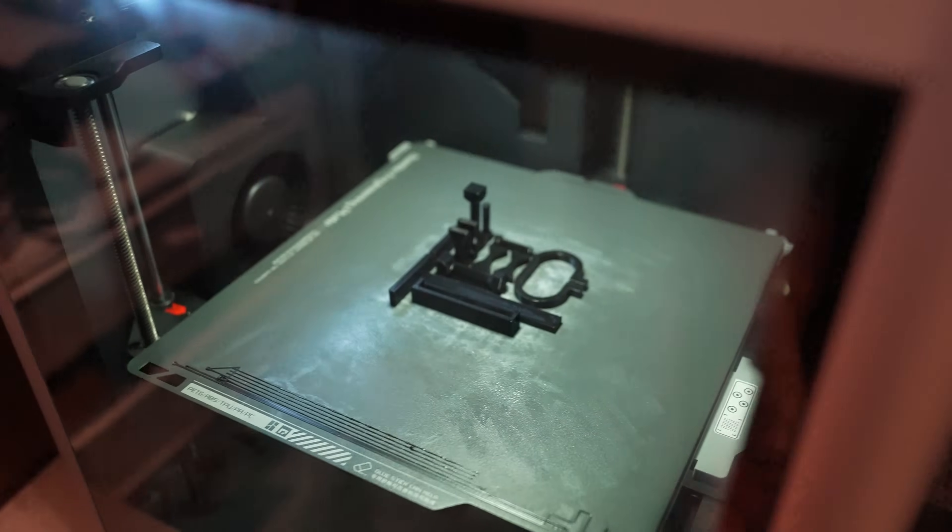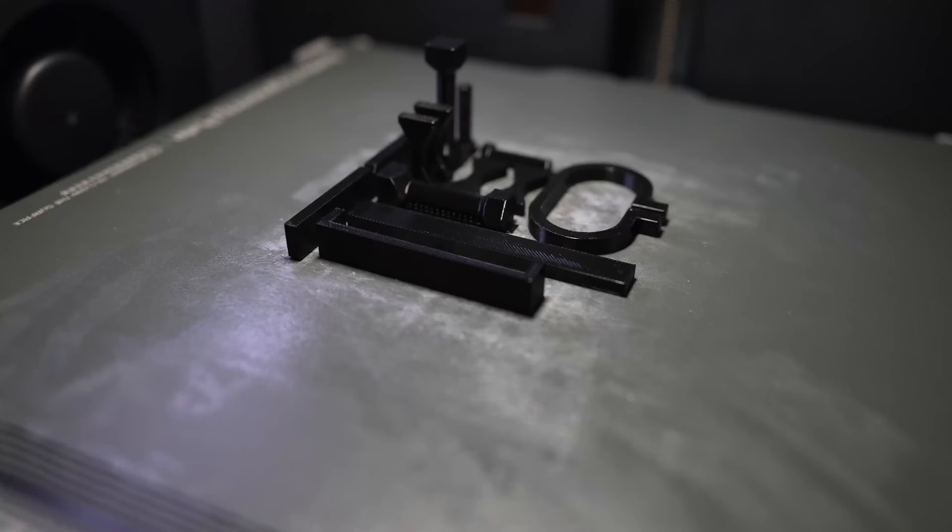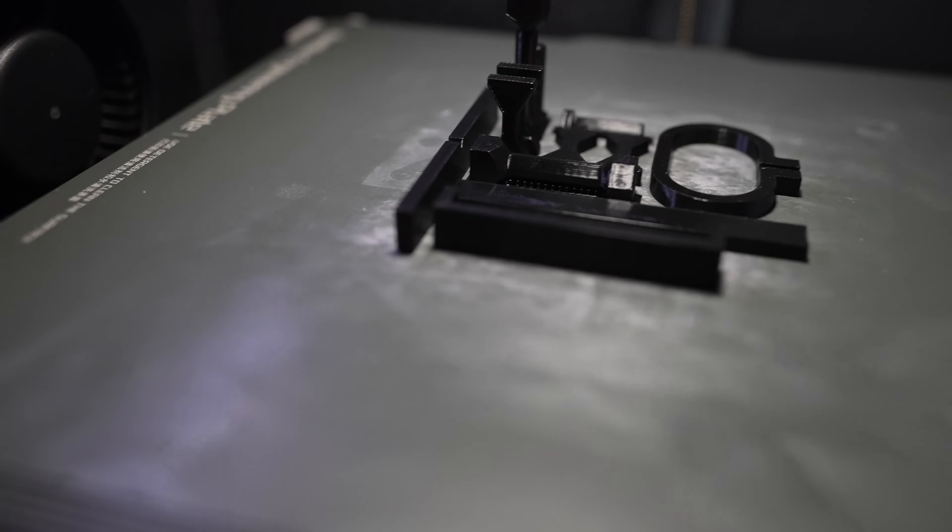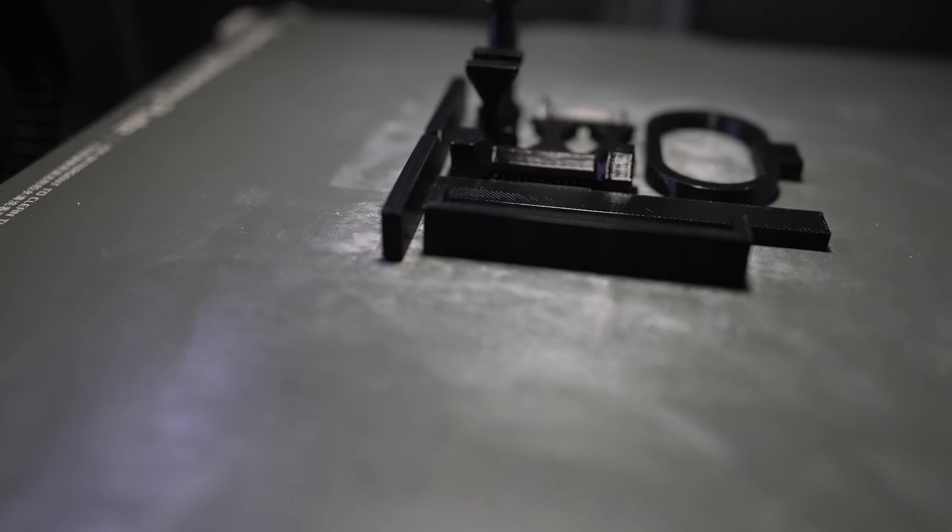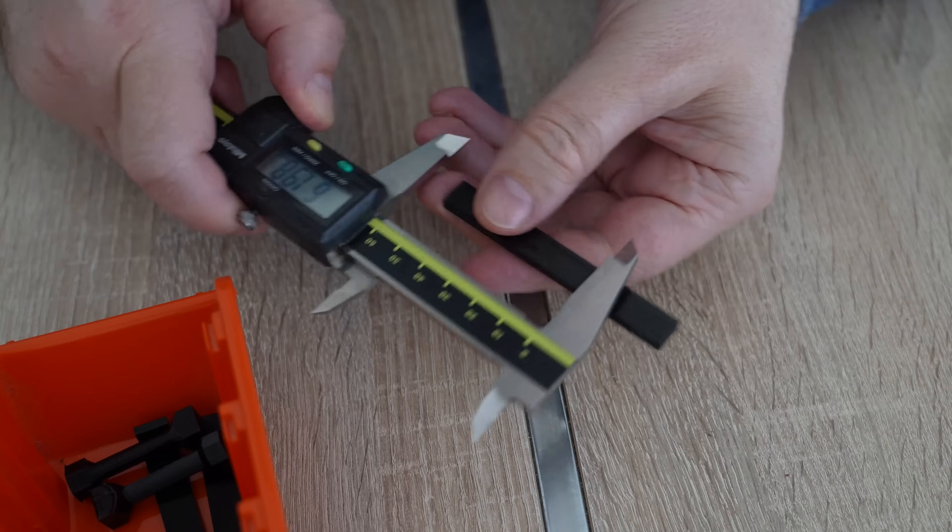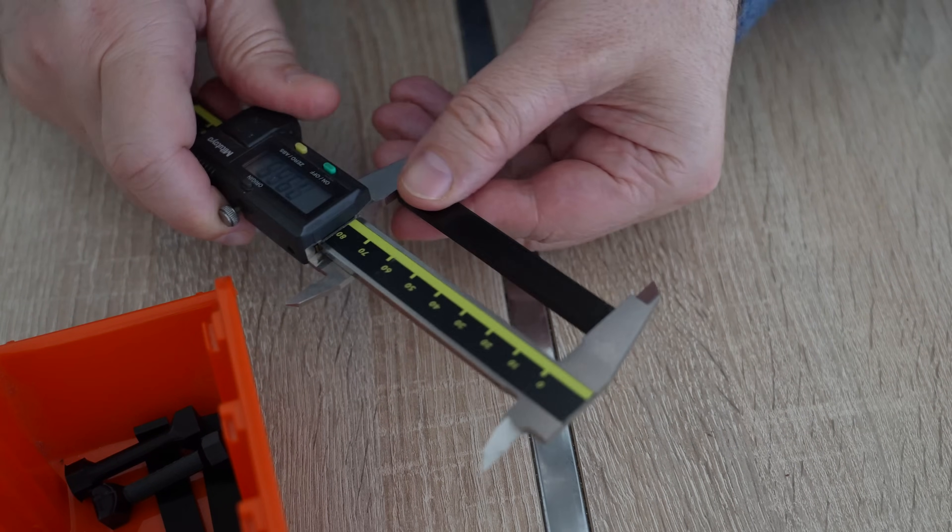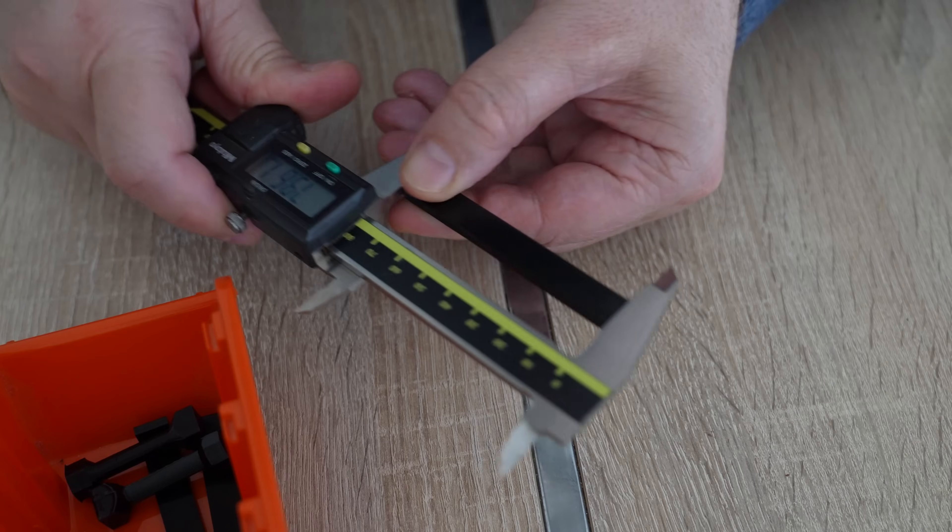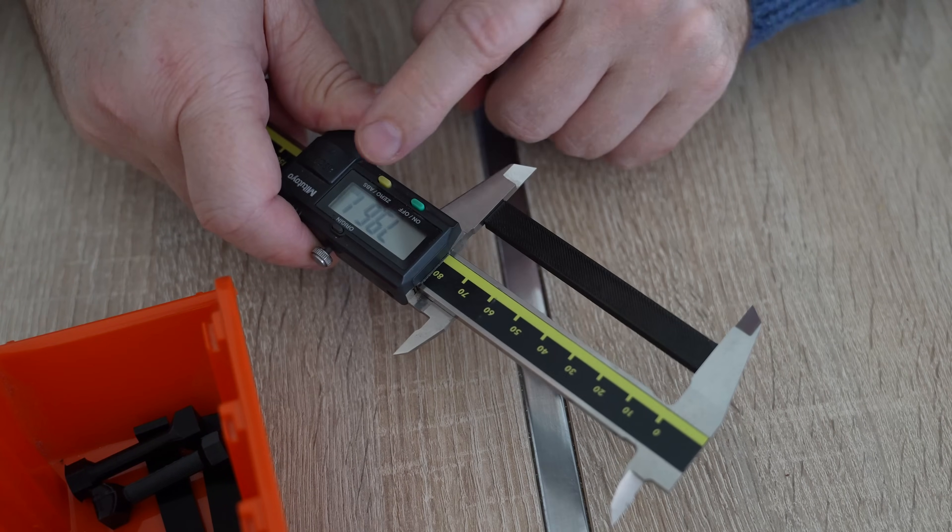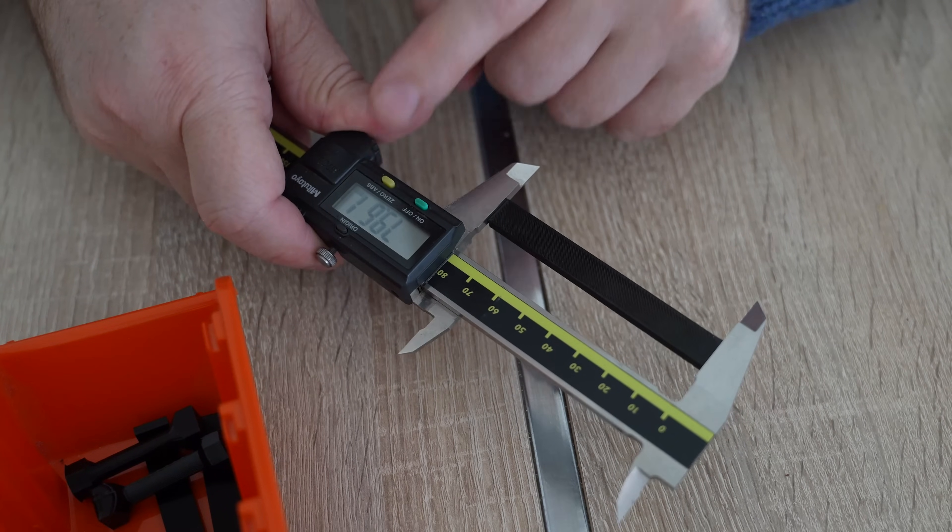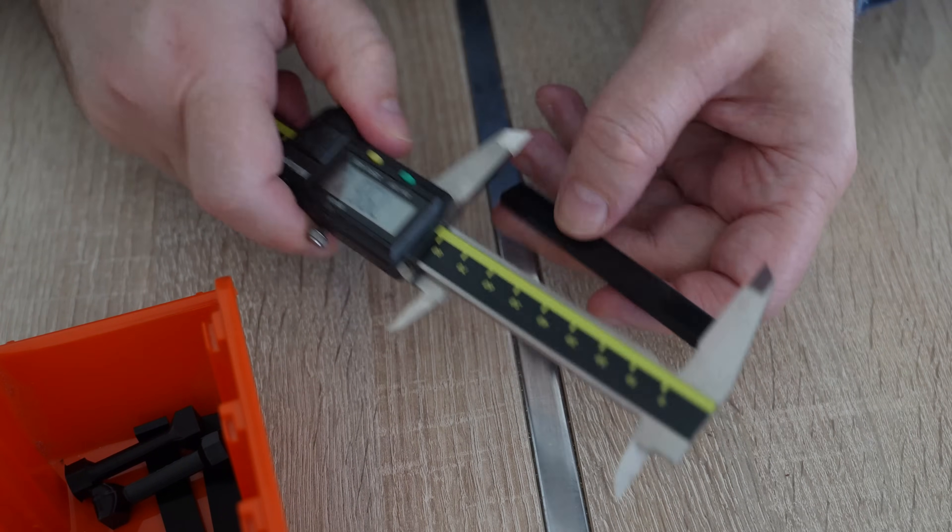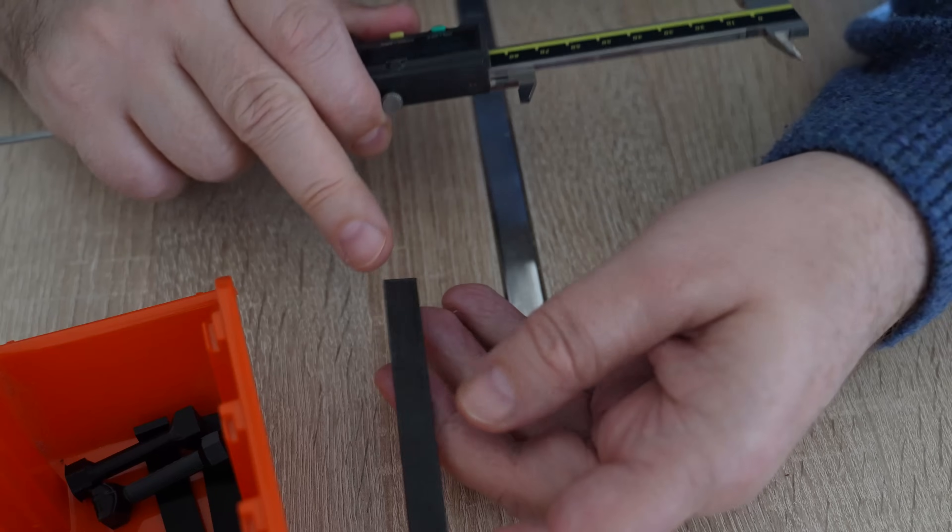Printing is finished and the object looks very nice. Just quickly to check the shrinking - I am measuring for elephant foot. The design length is 80 millimeters. 79.61, that's approximately half a percentage of shrinking, which is very similar to average ABS.